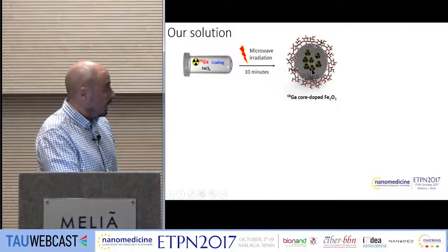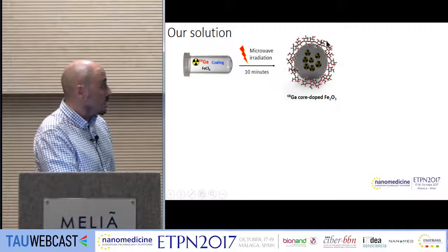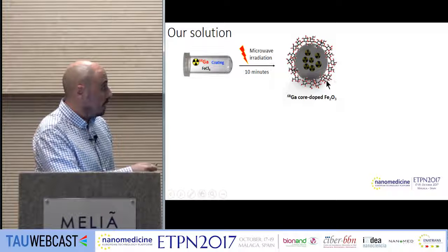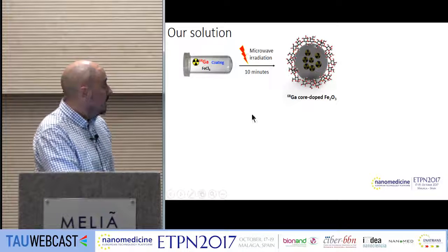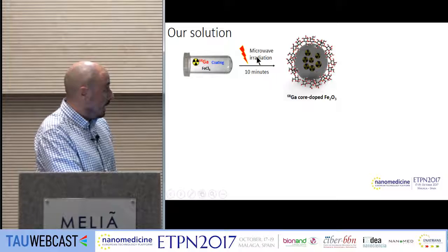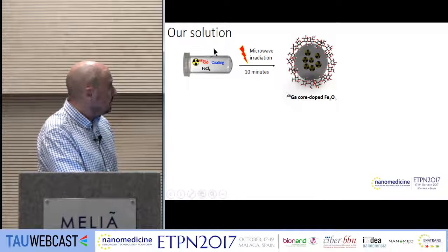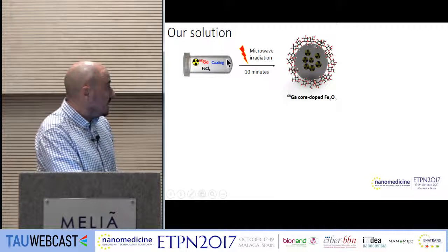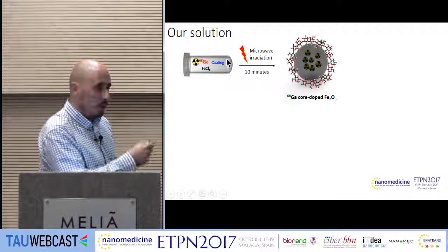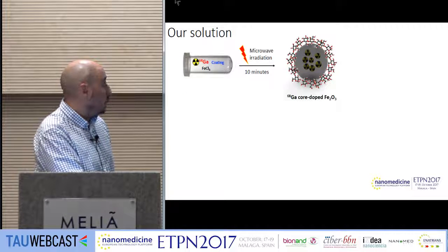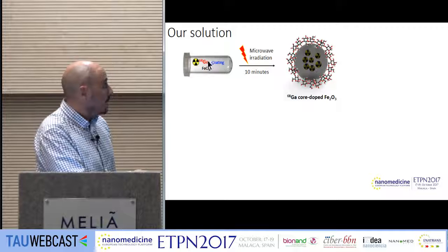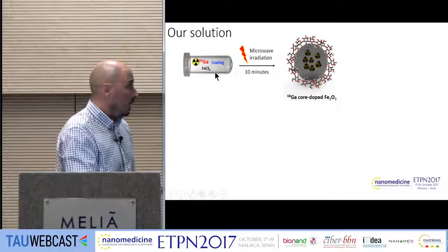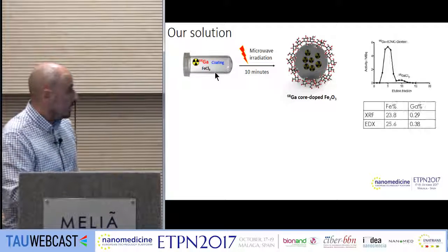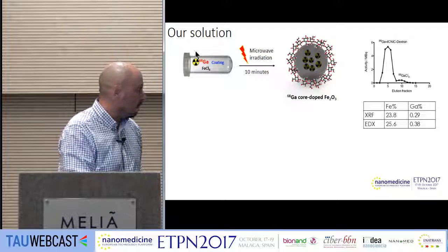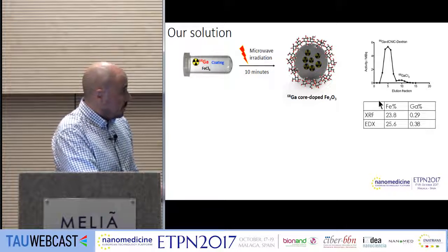Very small ones, we are around 3 nanometers in core size, with a very thick organic layer of around 10 nanometers. In one single step, by microwave irradiation, in 10 minutes, we mix the coating agent, whatever we want. We have done this with polymers, small molecules, the iron chloride precursor, and gallium-68 from the elution of a generator. We obtain these nanoparticles. We purify them by different means, mainly by size exclusion chromatography.